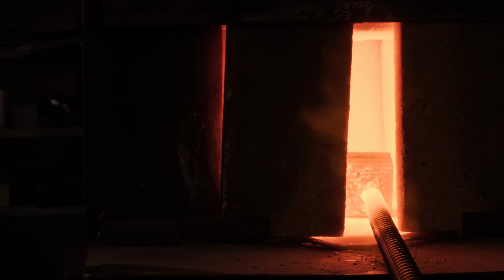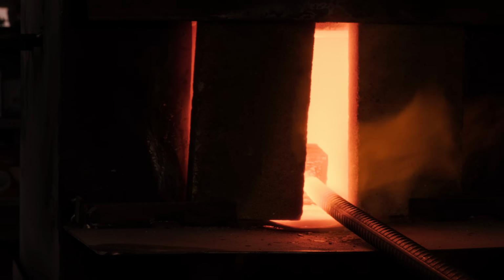But what you're doing, you're getting those layers pressed together as much as possible. You know they're clean because you've cleaned them. You've degreased them, you've abraded them, you've pressed them. That's good. The tighter you can get them together before you put them into the forge, the less likelihood there is of any air or oxygen getting in there to create oxides on the surface. So now that's it ready, and now we've got to get our forge nice and hot and get the right atmosphere inside there to get ready to weld.